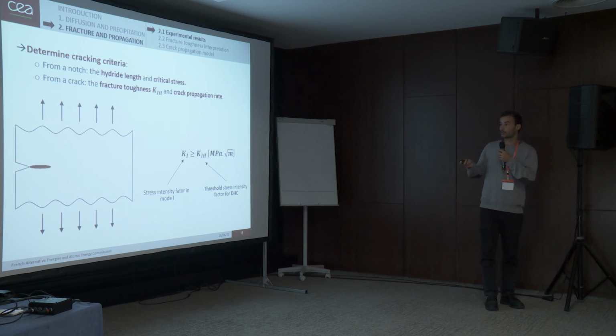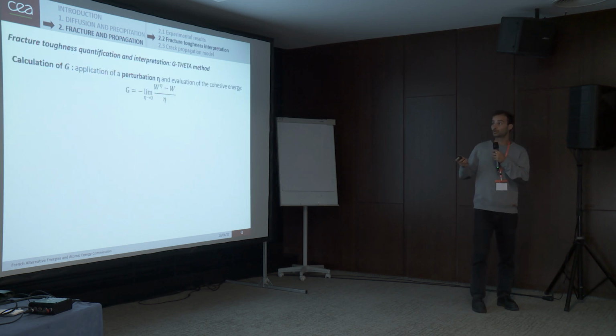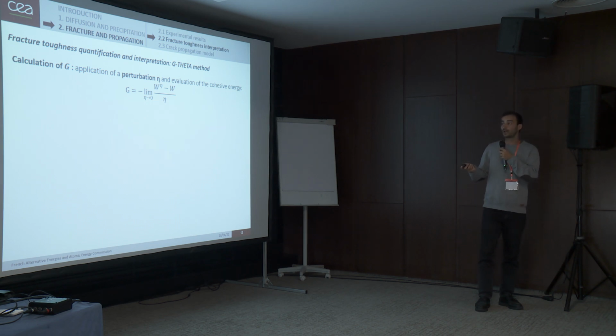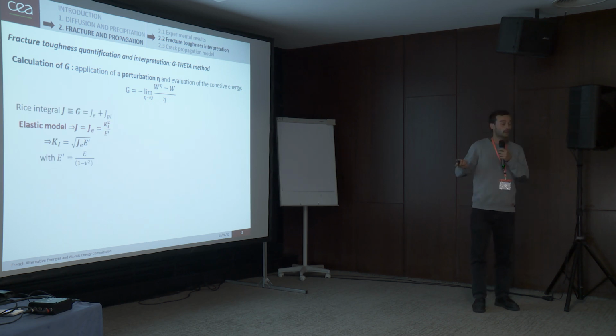So there are 2 cases. From a notch, we want to determine the hydride length and the critical stress, and from a crack, the fracture toughness, called the threshold stress intensity factor for DHC and crack propagation. So to quantify the fracture toughness, we use a numerical method called the G-theta method. It consists of calculating G, the energy release rate, by applying a perturbation eta, and we know that this value is equivalent to the Rice integral, which is divided into an elastic and a plastic term.